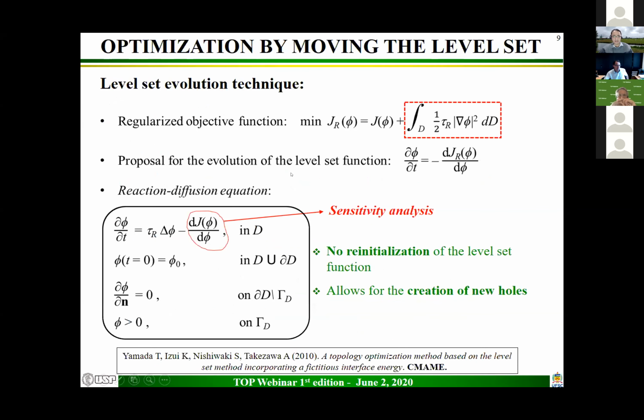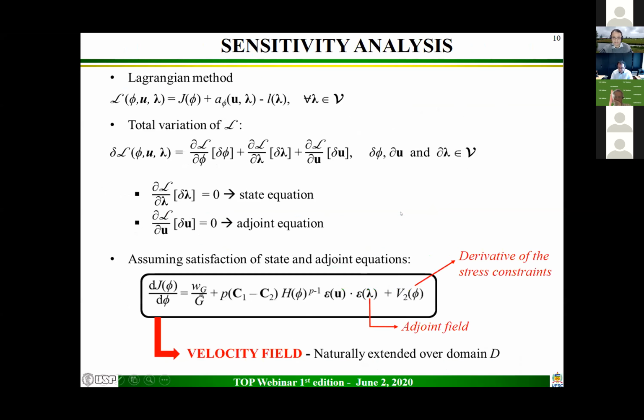Regarding the level set evolution technique, we have defined this regularized objective function, where essentially we add this regularization term to the original objective function, and the evolution of the level set is given by the derivative of this regularized objective function, resulting in this reaction diffusion equation. So this method requires no reinitialization of the level set function and allows for the creation of new holes. And this term here is the so-called reaction term, which is obtained by using sensitivity analysis.